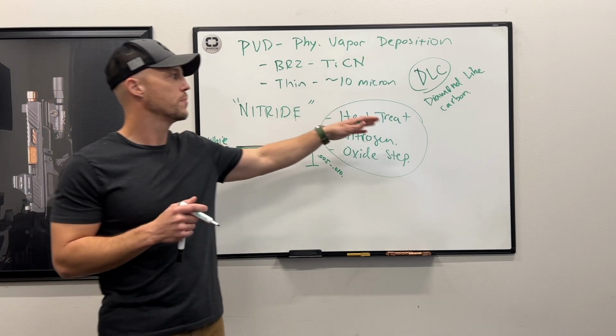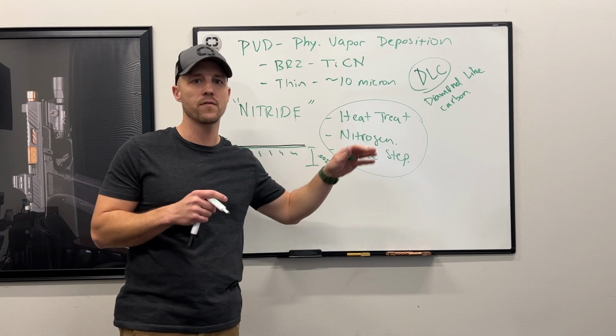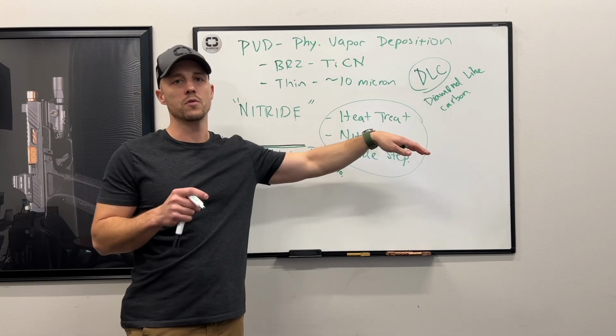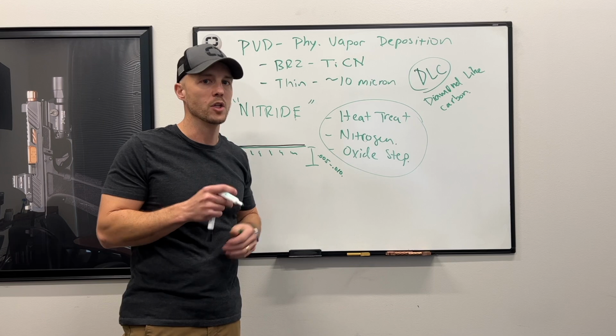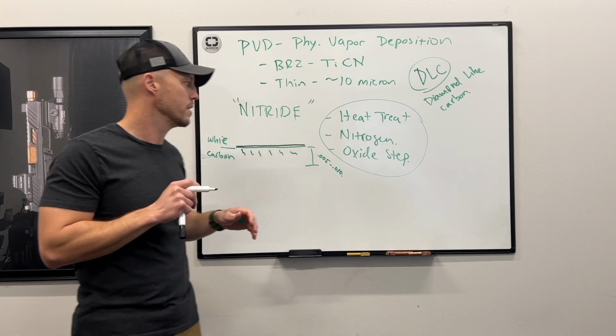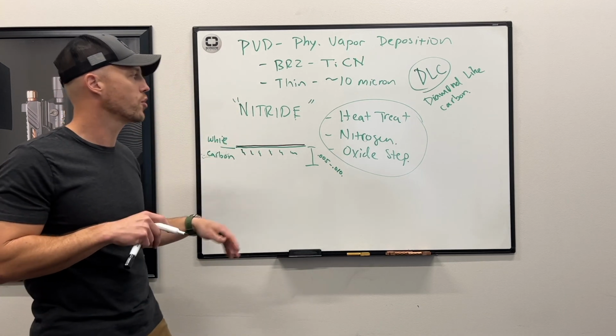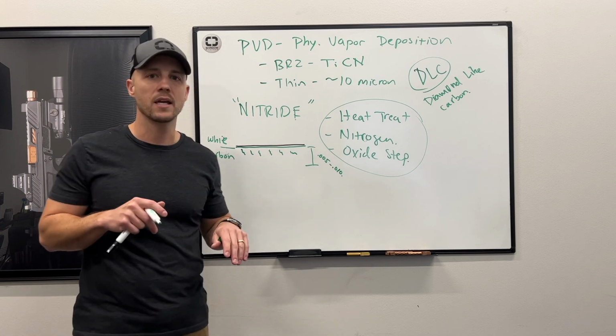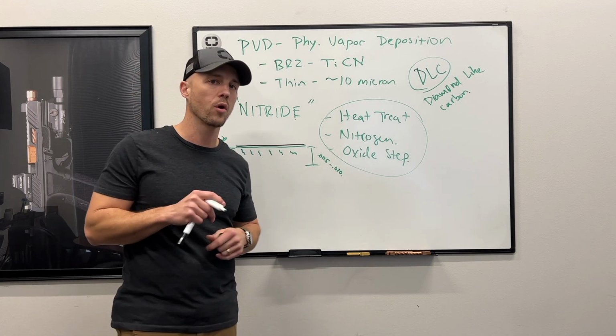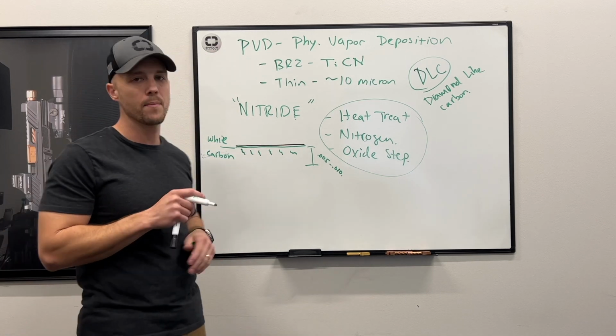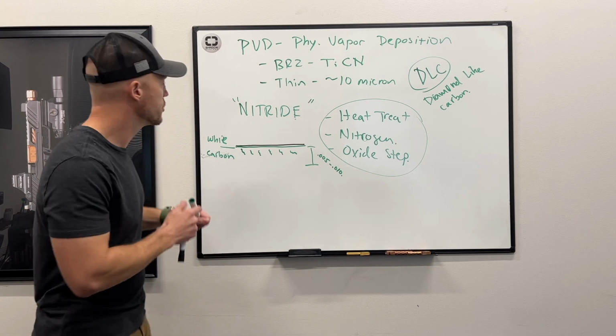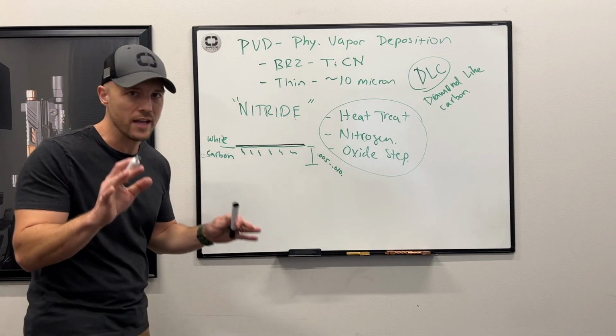Whereas a DLC part, even over a hardened 17-4 stainless steel, is just more prone to being damaged because it's not as hard at the surface. Okay. One thing you've got to watch out for with nitride is you want to make sure that your processing for the heat treat doesn't soften up the core of the part, but that's all dependent upon the material you're using. Okay. You'll also see this called, and there are variations of nitride,